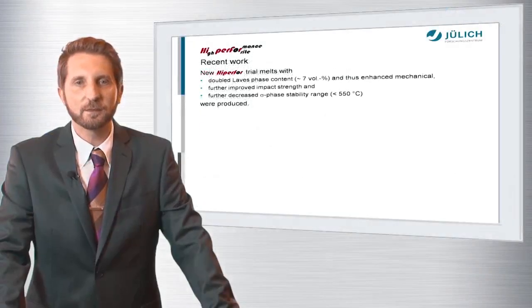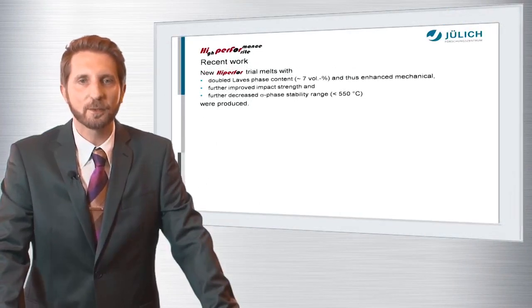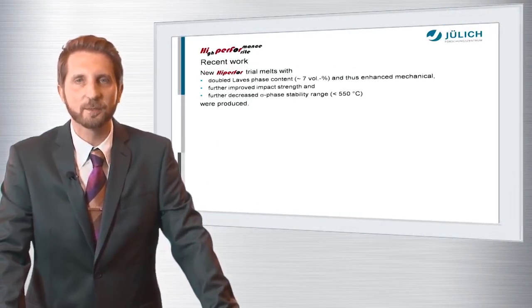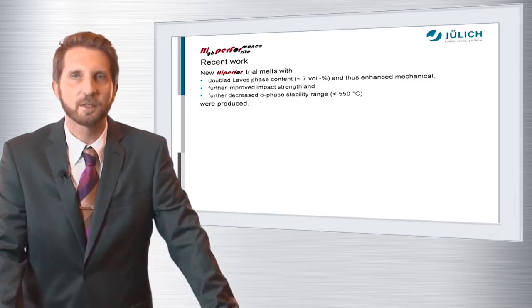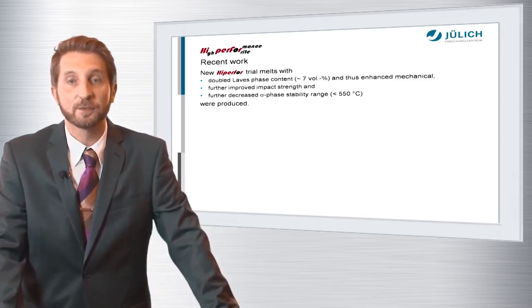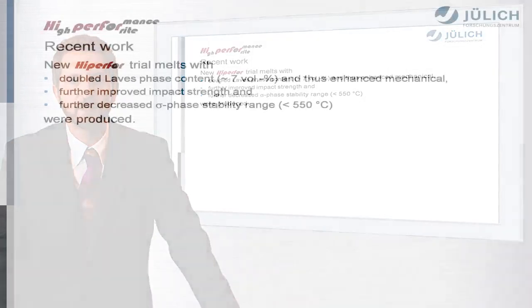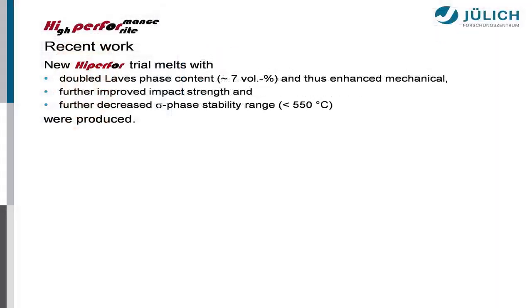So, for this reason, we produced a couple of new trial melts with approximately double Laves phase content of about 7 volume%. For this reason, these materials will have enhanced mechanical and further improved impact strength properties. And we're going to further decrease the stability range of the undesired iron chromium sigma phase to temperatures of approximately below 550 degrees C.